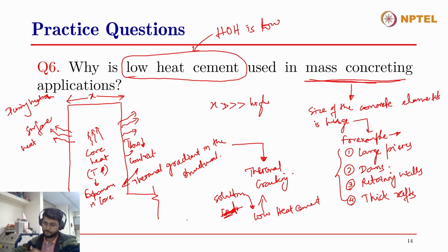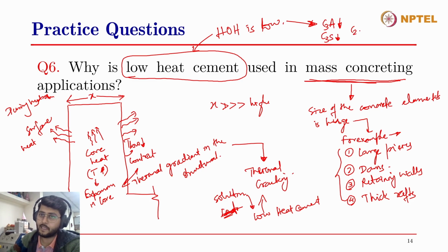Now what is low heat cement? Basically, as we mentioned, the heat of hydration is low. Heat of hydration will be low when the C3A content is low. So typically low heat cements contain low C3A content, low alite content, and high belite content, because we want ultimate strength, a later age strength. We don't want it to have a high heat release in the first few hours of the pouring of concrete. So we want to keep the heat of hydration very low, so we reduce the aluminate content and the alite content, while we keep the belite content high, so that we ensure a high later age strength as well. So this is why we use low heat cement for mass concreting applications.